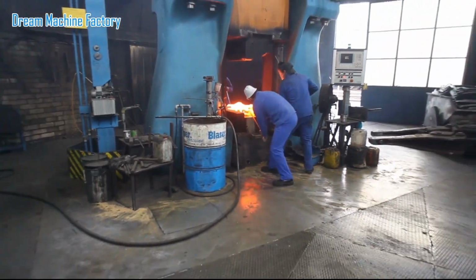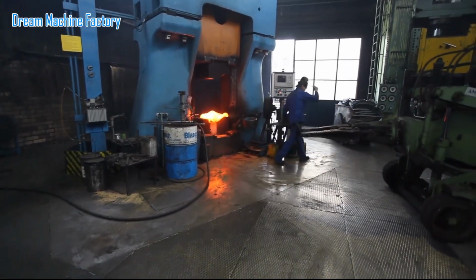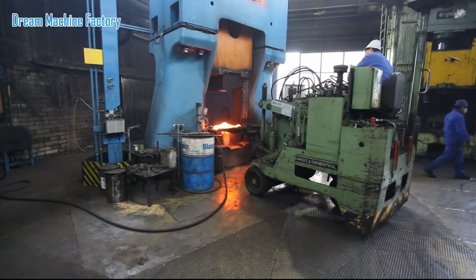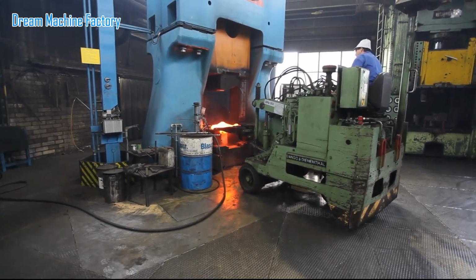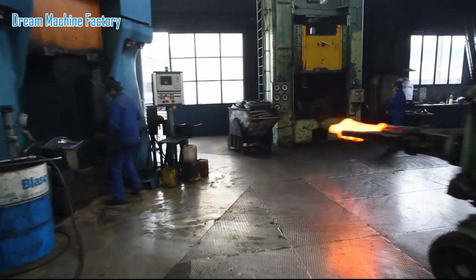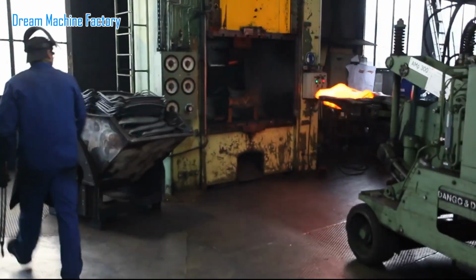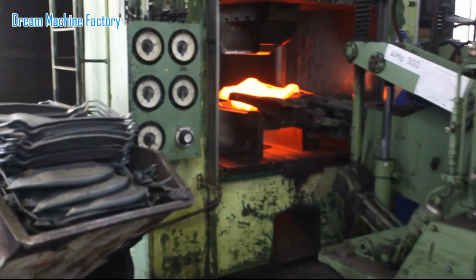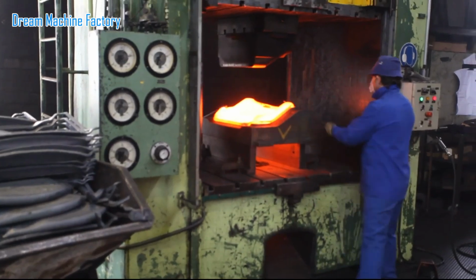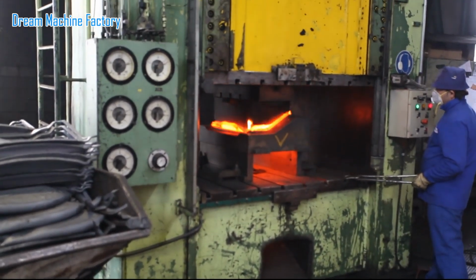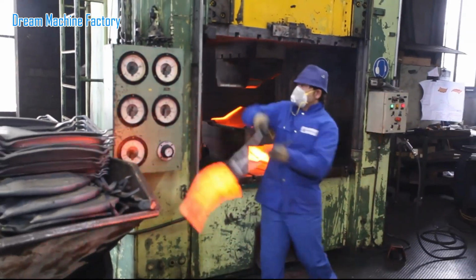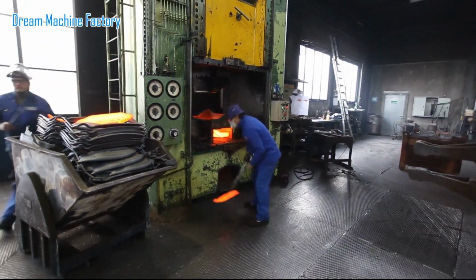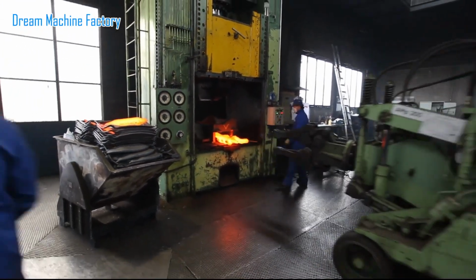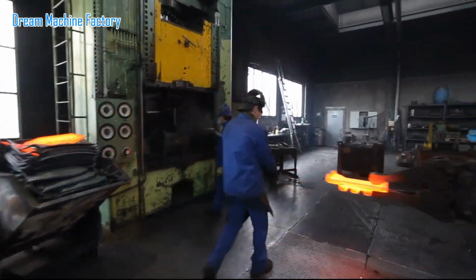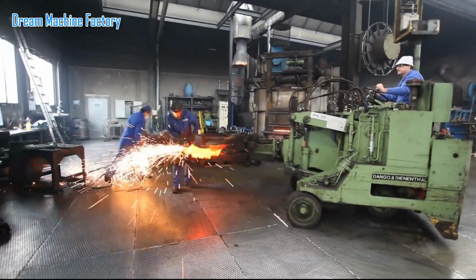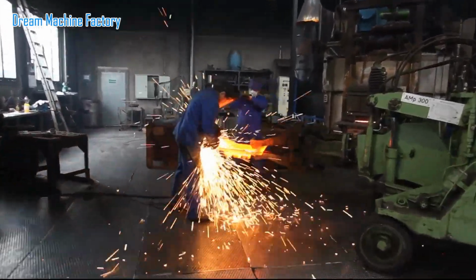Following pre-forging, the component is subjected to die forging using an electro-hydraulic drop hammer with a striking energy of 1,250 kilojoules. This hammer, manufactured in 2003, performs the detailed shaping of the part within a specially designed die. Interestingly, the size of the component exceeds the optimal capacity for this particular hammer, presenting a unique challenge. To achieve the final shape and required mechanical properties, more than 100 hammer blows are necessary.